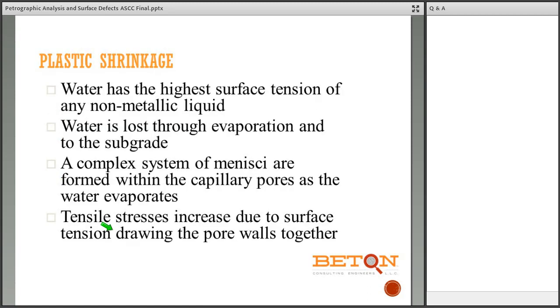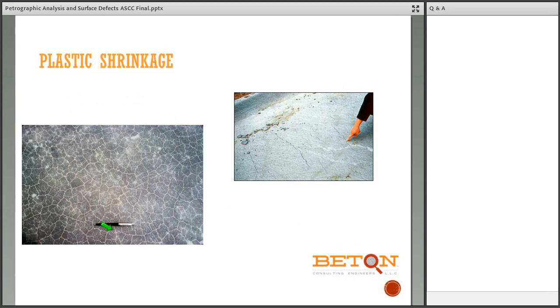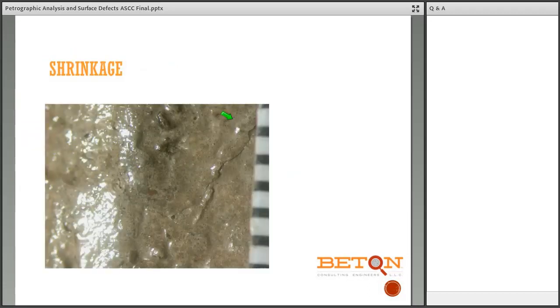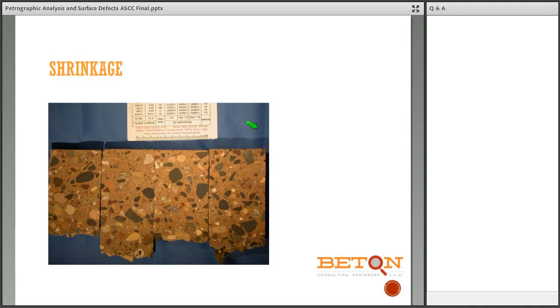We see plastic shrinkage, so you have some cracks that can be diagnosed by looking at the structure but are confirmed by petrography. Plastic shrinkage is typically more along the lines of cracks in this direction; cracks going in both directions are going to be something else, but these can all be confirmed as to the origin by petrography. Similarly, in this very detailed close-up, we can see a crack that is tapering off. The scale on the side here is in millimeters. So we have a situation where we have very fine cracks, and you can start to attribute what their cause is.